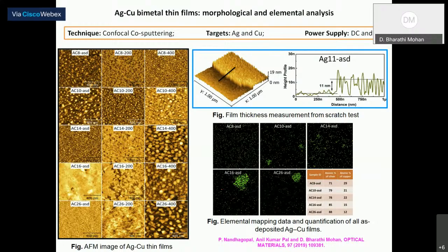Now, I am going to discuss the fabrication of silver copper bimetal thin films. And the corresponding morphological and elemental analysis is shown here. The silver copper bimetal thin films have been prepared using the confocal sputtering technique. Here we used silver and copper as targets, and we used DC and RF power supplies. So DC is connected to the silver, whereas RF is connected to the copper target. The elemental composition of silver and copper has been varied by increasing the DC voltage of the silver, keeping the RF power constant for copper.